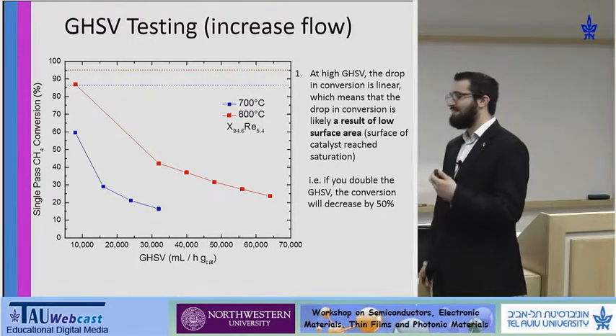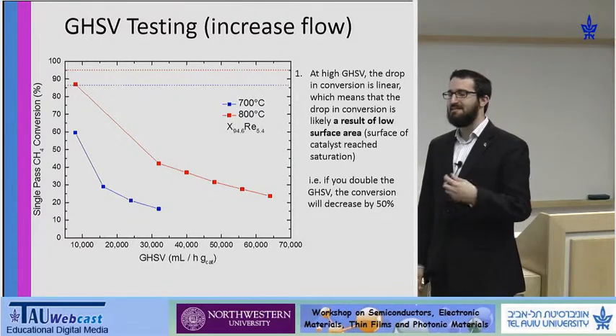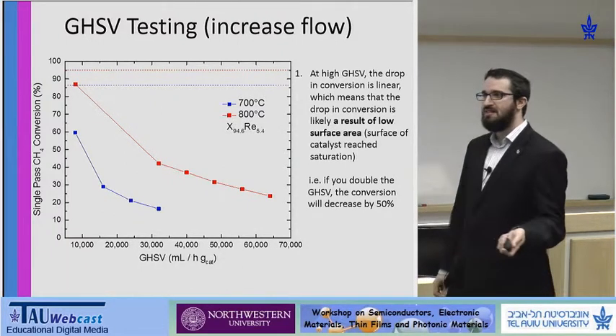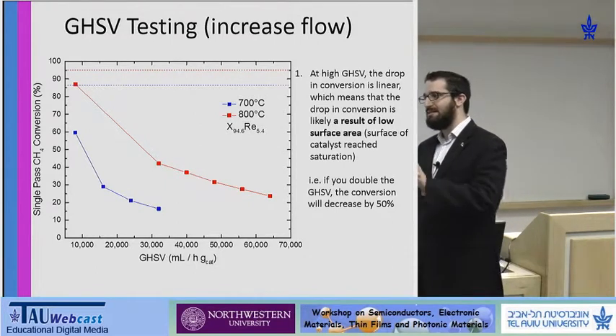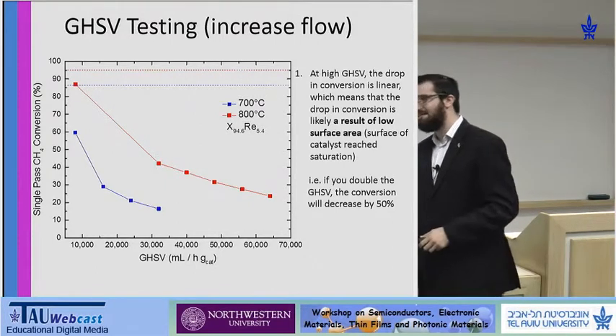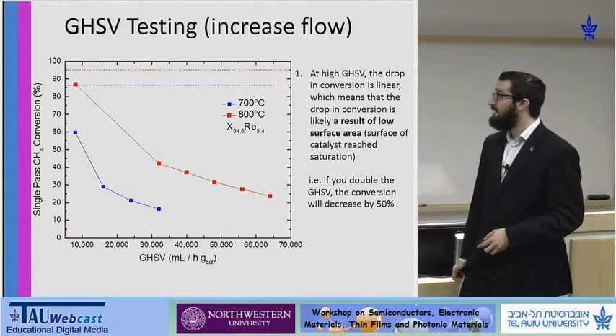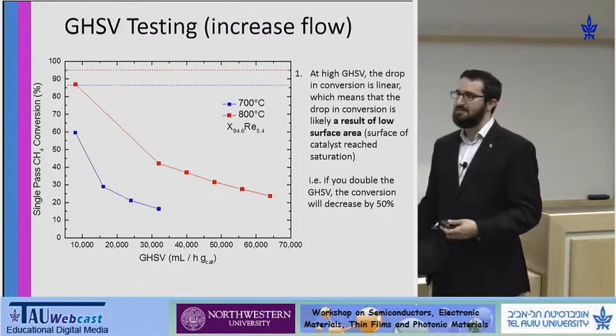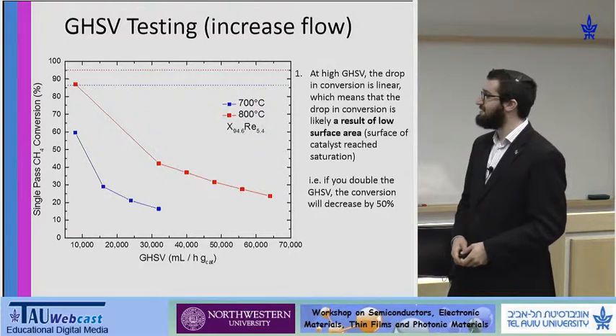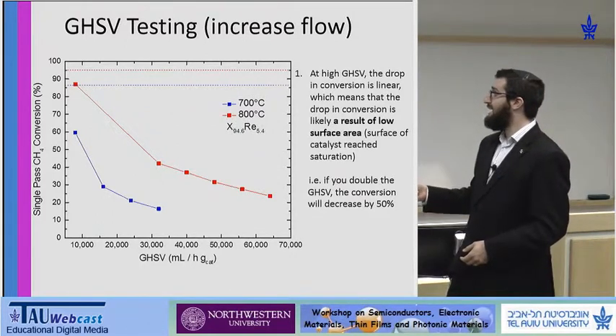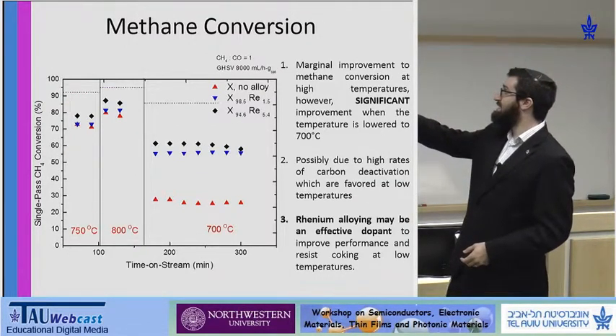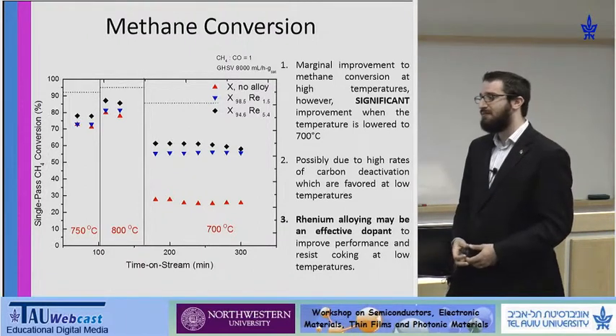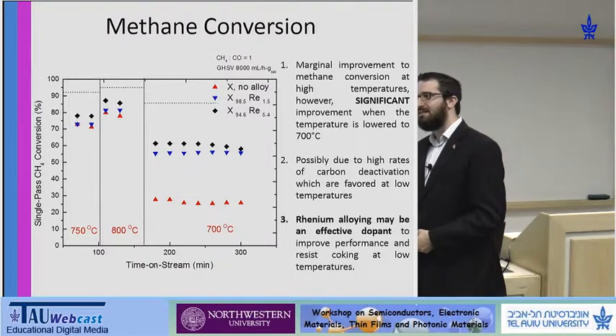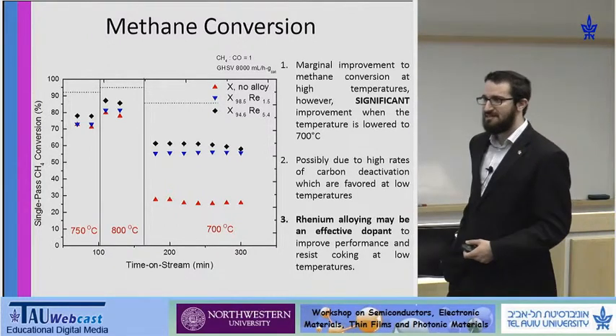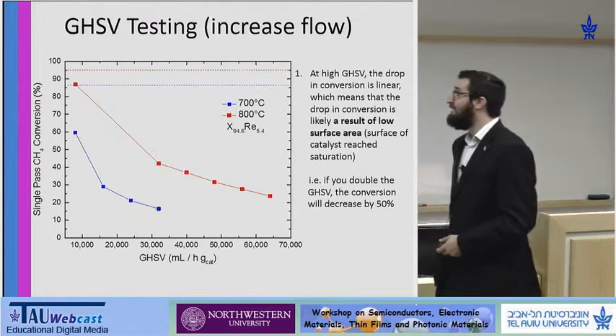What's also of interest is what's called the gas hourly space velocity. Briefly, it is the amount of gas that 1 gram of catalyst sees in an hour. So a gas hourly space velocity of 8,000 means that 1 gram of catalyst sees 8,000 milliliters of gas in 1 hour. And this is a way of standardizing your comparison between different gas phase catalysts. We're operating at a gas hourly space velocity of about 8,000, which compared to powdered catalysts is a little low. Powdered catalysts will generally run experiments closer to 20,000, but this is due to their higher surface area. They can process more gas.